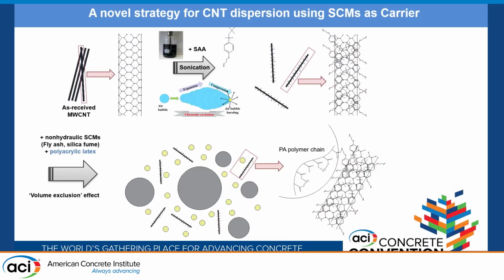So going from there, we said, can we just change things a little bit? So we added latex particles, because before we had another project dispersing CNTs in latex, and it was fairly successful and easy to do, and latex is added into concrete. We said, why not? We basically used a polyacrylic latex polymer, hoping some of those functional groups on the latex polymers would associate with the dispersant and attach it to the SCM surface. So we simply, again, mixed those ingredients, and separation happened again. And this time we simply added another layer of latex to separate it from everything else.